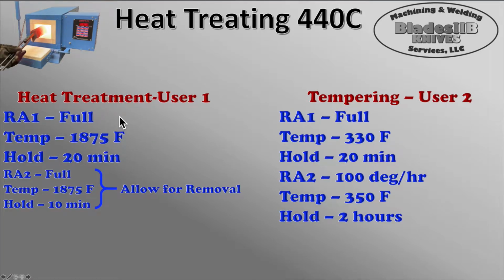Again, for my kiln, just full speed ramp. So ramp 1, full speed, as fast as it can heat it up, get to 1875 degrees, soak for 20 minutes, open the door, pull it out, air quench it, and you're done. I have a second ramp set up for an additional 10 minutes, because I typically do 3 blades at a time, and that extra 10 minutes is for opening the door in between blades, for the time it takes me to get one cooled off and hanging on the nail, so it's still trying to keep the kiln up to temperature for that 5 or 10 minutes that it takes me to do all three. So that's why I've got this extra ramp set up.